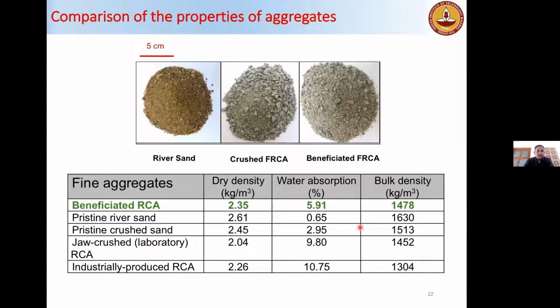Yeah. So here we have tried to compare the beneficiated aggregate with crushed aggregate or untreated fine recycled aggregate and the river sand. You can see that water absorption is around 6%. It is not comparable with the river sand, but definitely better than the untreated recycled aggregates. We have also tried using this aggregate in concrete.